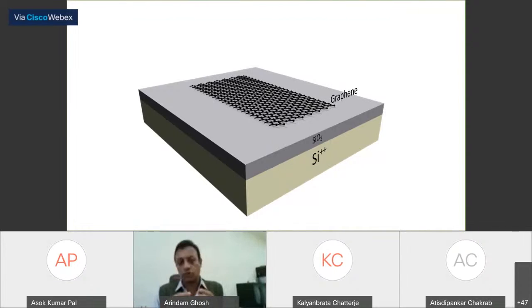That happens because silicon is, after all, a three-dimensional system. So what people would like to do now is thin down the channel width as much as you can, so that you can go to the off state far more efficiently, and all these thickness-induced problems like drain-induced barrier lowering and others are minimized. You also get new architectures like tunnel field effect transistors and so forth.